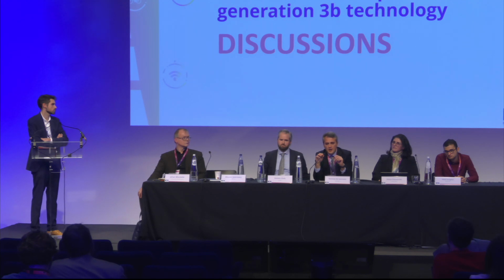Concerning the multi-layer, this consists in the application of several coating layers. So you can have a thicker and uniform layer of active material on the electrode, and you can achieve a higher areal loading. This is a way of increasing the gravimetric index of the cell. So this is expected to also give us a bump in terms of gravimetric energy index at cell level. We have explored this as part of an upgrade that we're doing on our pilot line. We have a different nozzle and we have applied some modifications to the coating machine to do that. And we see that we can achieve almost double the areal loading, which will not translate into double the capacity, but a good and non-negligible increase in the capacity at cell level.